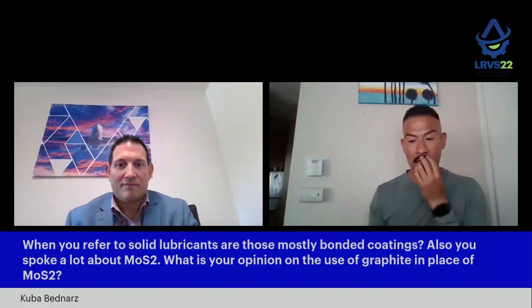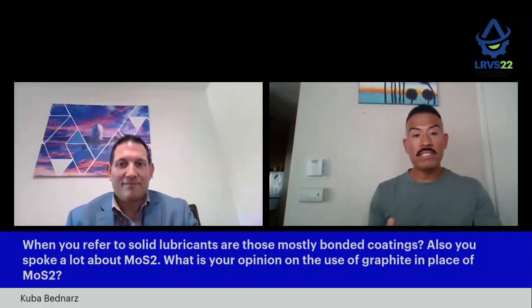Graphite is tricky, right? Molybdenum sulfide is really good under vacuum conditions because it doesn't like humidity. On the other hand, graphite needs humidity to work, right? So graphite is not the best lubricant for space applications. And it's also conductive, so it can even short circuit systems.